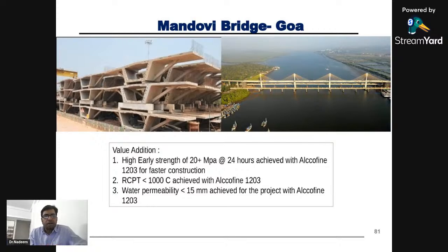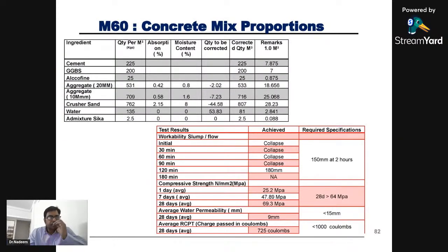There, their requirement for HPC was 20 MPa in 24 hours, RCPT less than 1000 coulomb, and water permeability less than 15 mm. Here also Alcofine is being used in that project. This is the concrete mix design. For M60 grade, the cement is only 225 kg, with 200 kg of GGBS and 25 kg of Alcofine. So nowadays, things are moving toward durable concrete.